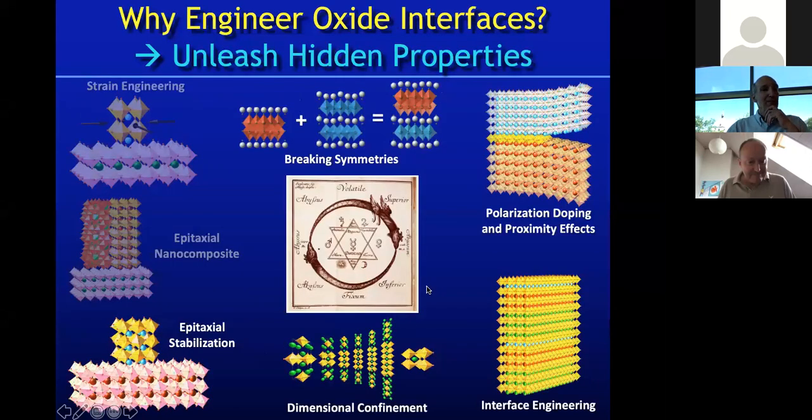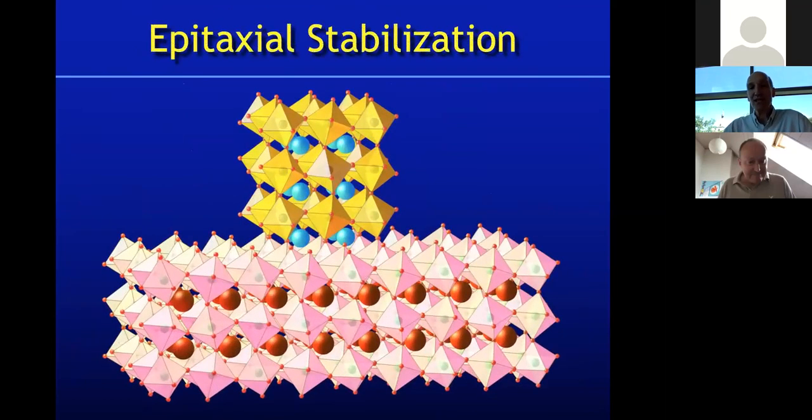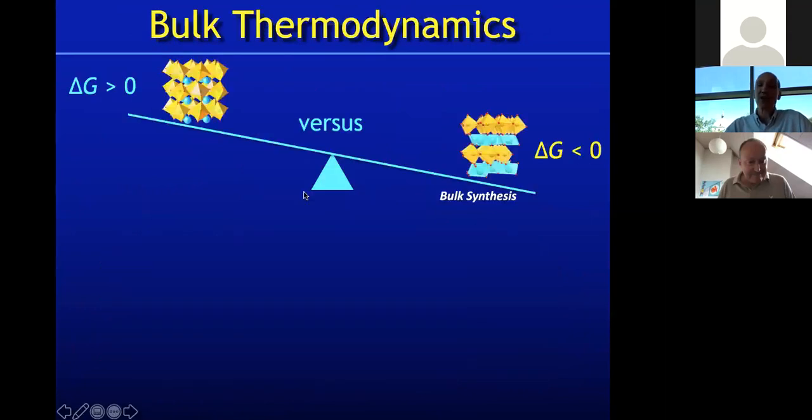or 3%. Okay, I want to move to the next trick, epitaxial stabilization. Now, you can see already the influence of the substrate, hopefully, on the film. And where this trick comes in is when bulk free energies are not on your side, okay? So it could be, and it often is, that the interesting structure, the structure that you expect, based on theory or intuition, to have possibly great properties, might be the one that's the metastable structure,